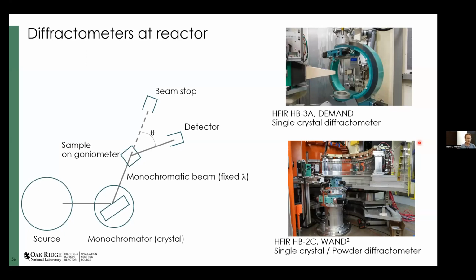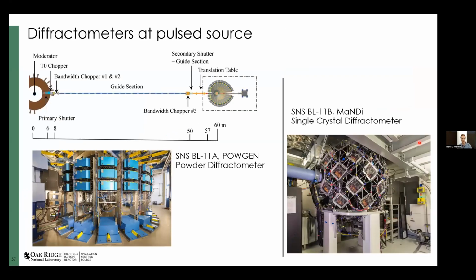At a pulse source, it's very different. On the left, you have our powder diffractometer, our high-resolution instrument. The instrument is at 60 meters away from the source. That gives the pulse time to spread out. You can select a certain part of this, and the entire range of wavelengths hits your sample, and you measure at a time of flight and around it. A very efficient way to collect a lot of information for multiple wavelengths that you can then calculate back what it really means. You can have detectors arranged in certain geometries.